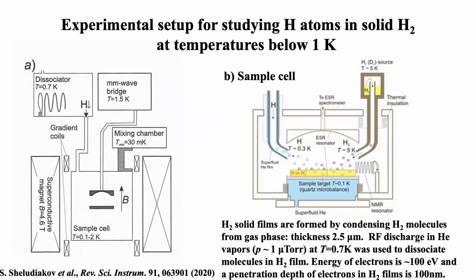Initially we grow the film. Usually we grow a film with thickness of 2.5 micrometers, I will explain why later. After we created the film, we sent some quantity of helium gas. Why are we sending this gas? To start the discharge, because the pressure of hydrogen at these temperatures, 10 to minus 15, you cannot start discharge there. So you send the gaseous helium, start discharge, and when discharge is running, the electrons created in discharge bombard the H2 sample and create atoms on the surface of the sample. We know the energy of the electrons, approximately 100 electron volts, which allows the electron to penetrate inside the H2 to a width of 100 nanometers.